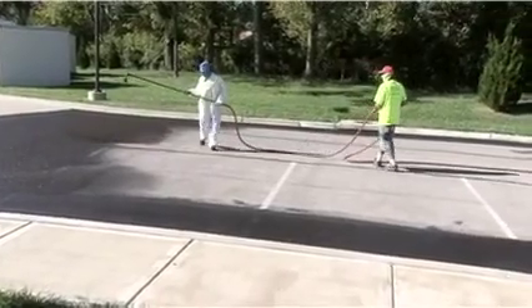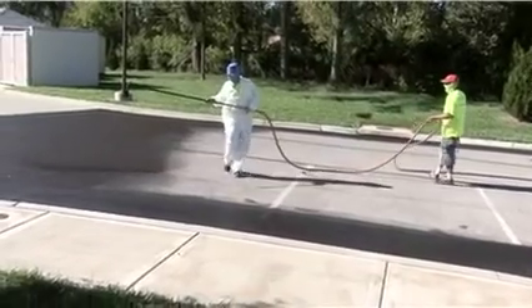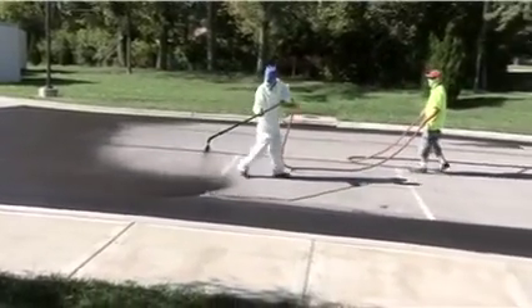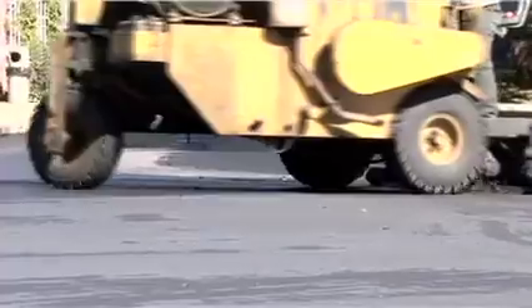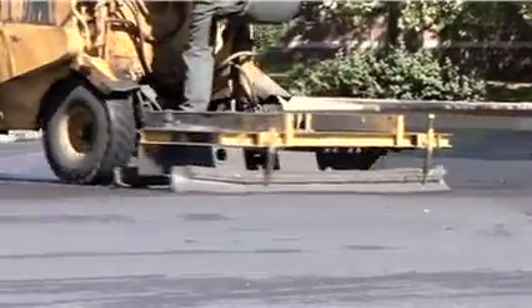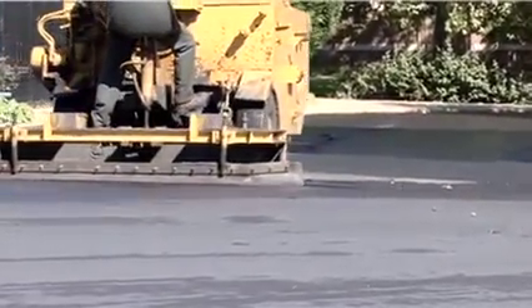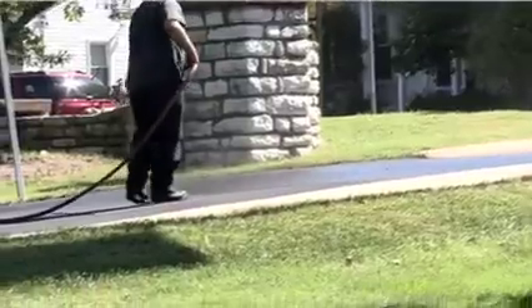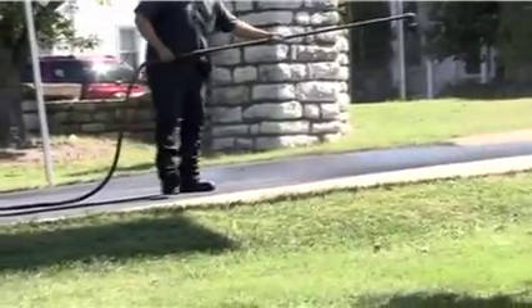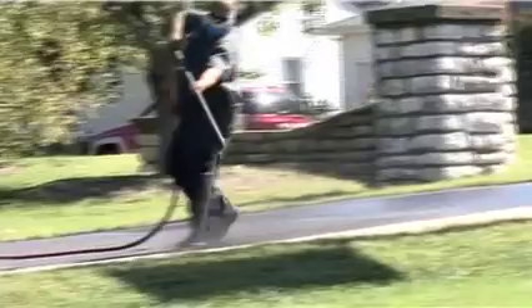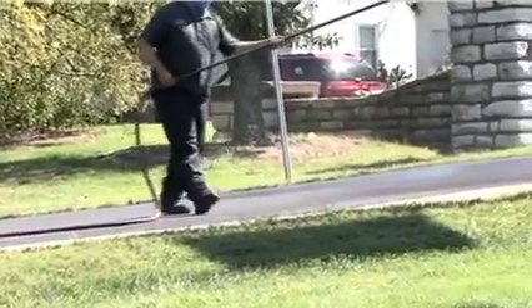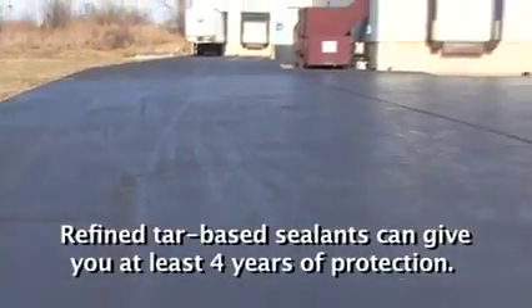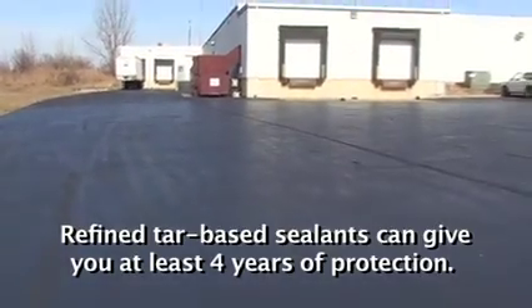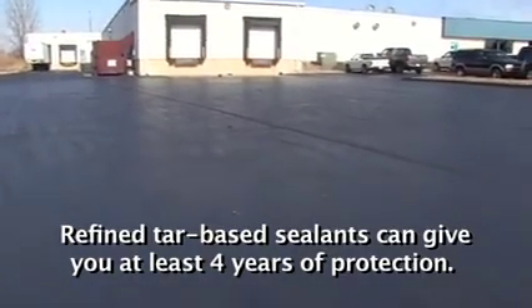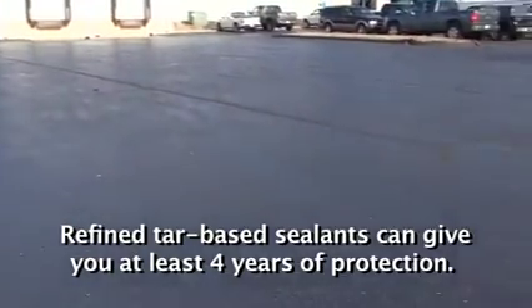I also believe that the longevity of the product is based on the application, how it's applied, whether it's sprayed or whether it's squeegee applied. In our particular case, we like to squeegee apply the first coat to fill the pores of the asphalt, and then we spray apply a second coat, which is what we call a wear surface. And on a given parking lot, if that application's done correctly on a standard parking lot, I have no problem telling a customer that we're going to garner at least 4 years out of it. And that's the nice thing about the refined based tars, is that, again, they'll keep their color for that period of time.